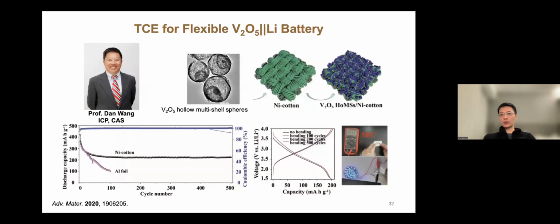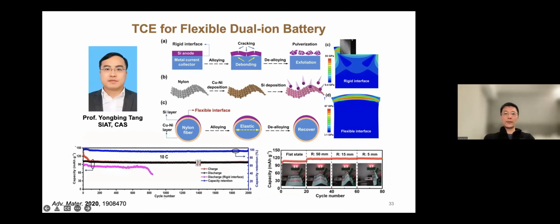I will show you a couple of quick slides about how we expand the TCE concept to other materials. For example, we collaborated with Professor Dan Wang at the Chinese Academy of Sciences, and we make use of the vanadium oxide hollow multi-shell spheres that they developed, and we extended their stability significantly. The problem with these shells is that the stability is not that good, even after they published a Nature Energy paper, and so we were able to address that issue a little bit.